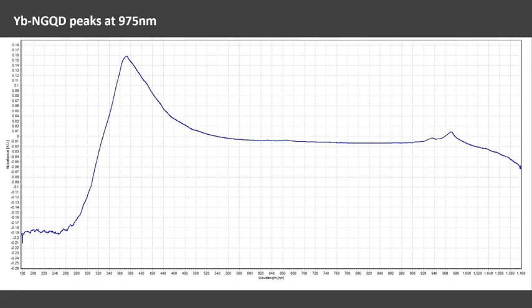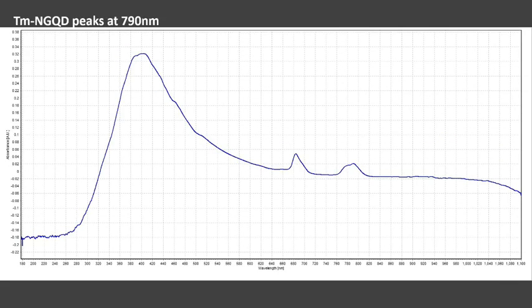For our ytterbium NGQDs, we see a peak over here at 975. Again, just looking in that 800 to 1100 range. For thulium NGQDs, here's where our 800 starts, and we go into the 1100. We don't actually see a peak in the actual near-infrared region. What we do see here is a peak in the shoulder at 790 nanometers, and we thought that might be close enough to see some photothermal properties in the thulium NGQDs.